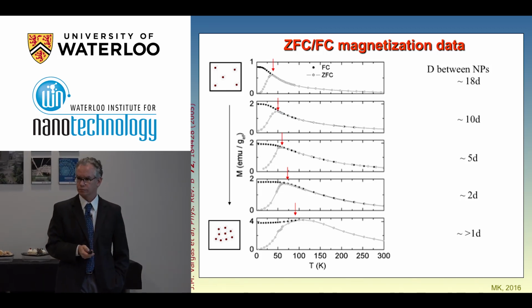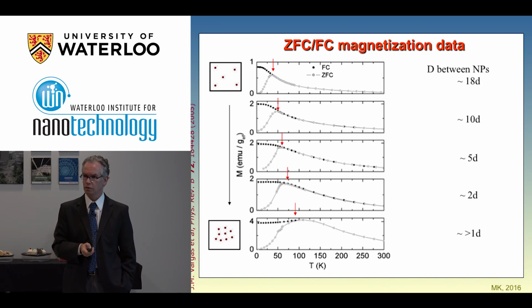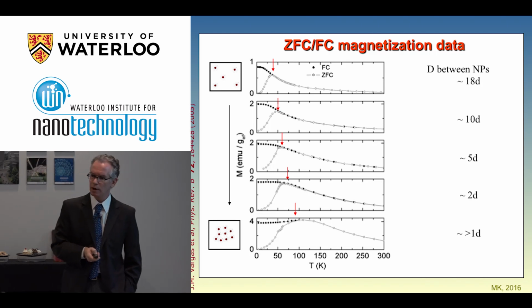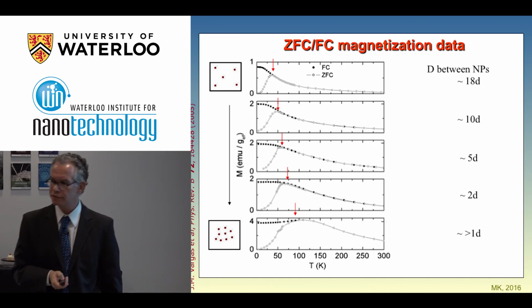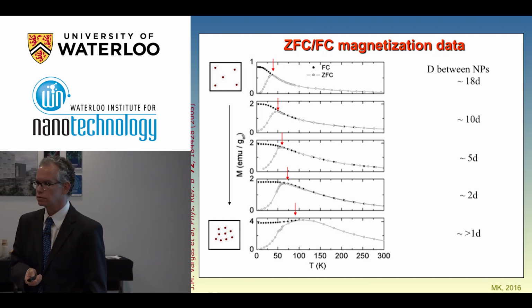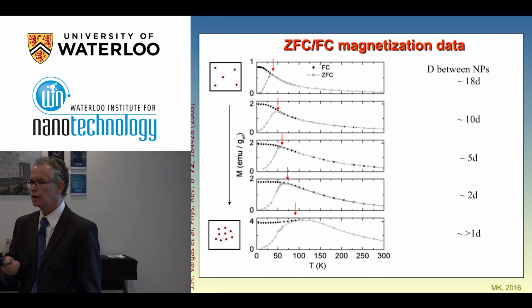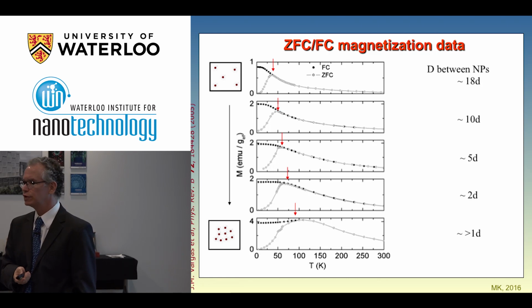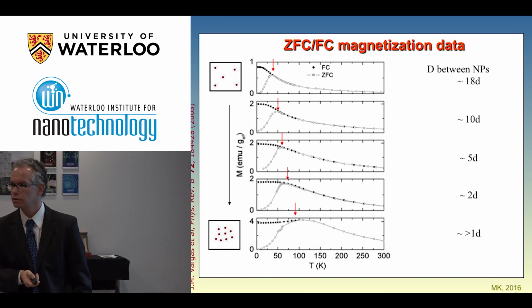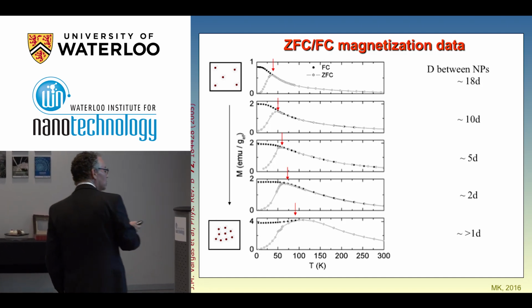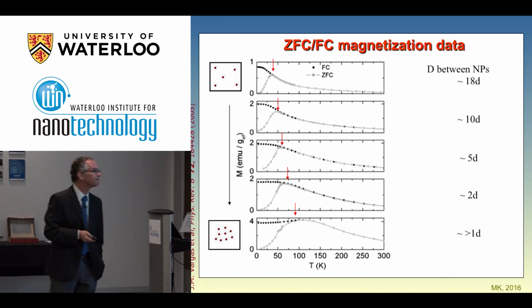What's the size of the moment on one particle? Of the one particle is typically 3,000 Bohr magneton. So it's about a few nanometers, from 3 to 5 or 6 nanometers of cobalt, for example. So it's a typical size of the samples.